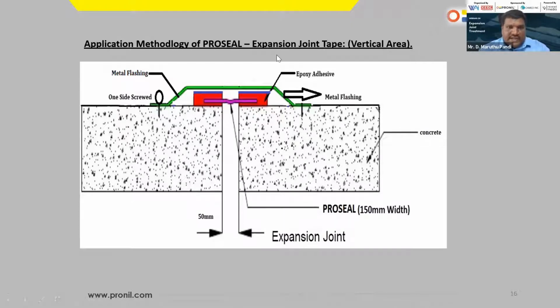And this is the application methodology of ProSeal of expansion joints on the vertical area. In the vertical area, you can leave the ProSeal exposed to sunlight, or you can apply some UV resistant coating on top of the tape. Up to 7 foot, where human accessibility is there on the floor as well as on the wall, we normally recommend a metal flashing to protect the tape as well as to protect the joint in the waterproofing systems. And that also should be one side screwed to have the movement accommodation factor. After 7 feet, you can avoid metal flashing. You can expose the products to the sunlight which is UV resistant, and also you can use some of the acrylic systems or any hybrid PU materials having very good UV property.